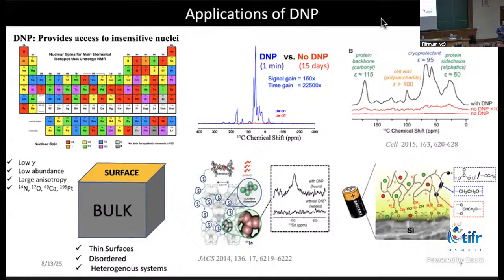The surface, can we resolve the radical on the surface? So it's no more the same surface. So the normal NMR of the surface versus the DNP NMR, the chemical shift, the signature, the shape, everything can change, right? Because of the presence of the radical. So there could be deshielding, shielding, all of those effects. So yes, how do we know that it is the same signal? So it does not have to be chemisorbed on the surface, and the reason will come because there is a thing called spin diffusion. So even if the radical, I'll come to that slide. Okay.